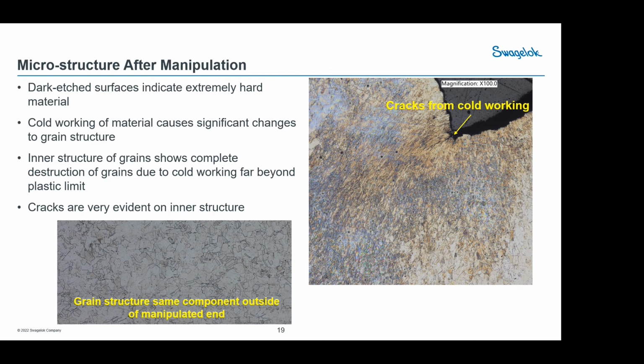And the biggest concern that we're concerned about is the fact that there's already cracks. There's a very large crack that's up inside this part already. In fact, under microscope analysis, there's 9 different cracks on the ID. Now, remember I said earlier that hydrogen likes to get down inside cracks where materials are breaking apart and help them break apart faster. It's called hydrogen-assisted crack propagation. And this can happen within this type of system.